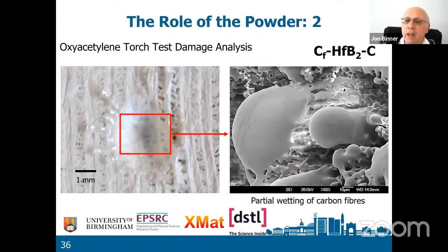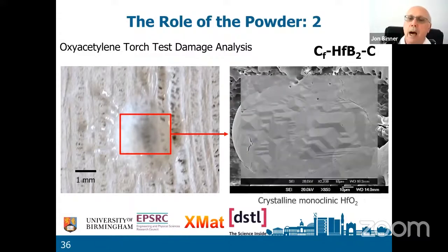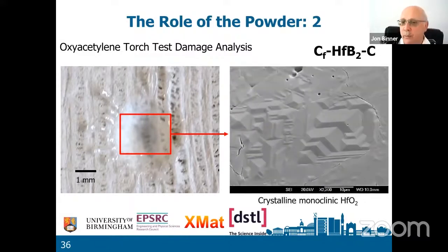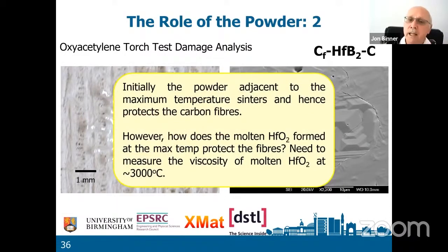And if we zoom in, you can actually see we have a non-wetting situation. So what was molten hafnia has formed droplets, and they are not wetting the carbon fibers. So we've got partial wetting. We think we can improve the performance if we achieve better wetting of the carbon fibers. And if we zoom in even more, we can see we've got crystalline hafnia. So initially, the powder adjacent to the maximum temperature sinters and protects the fibers.